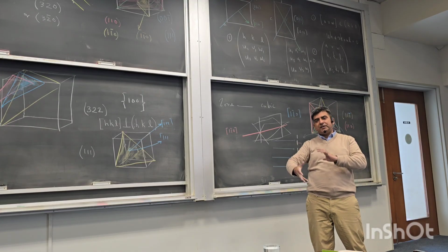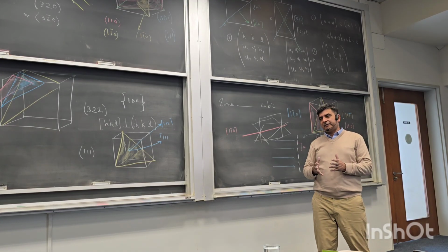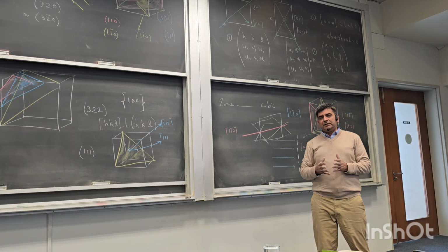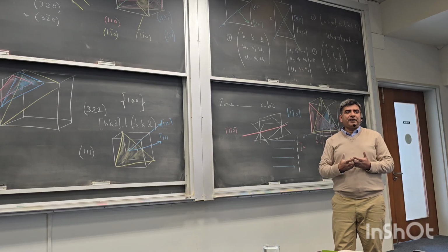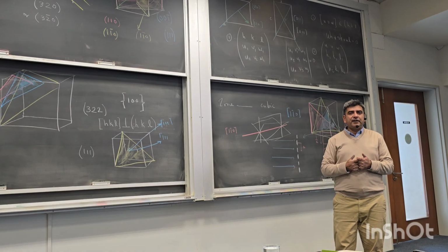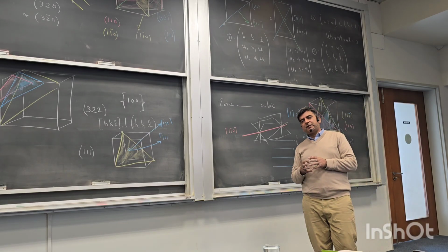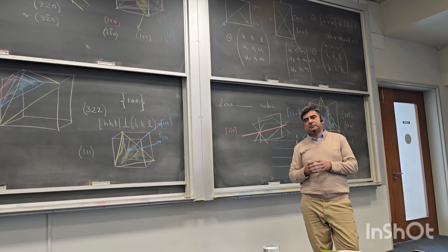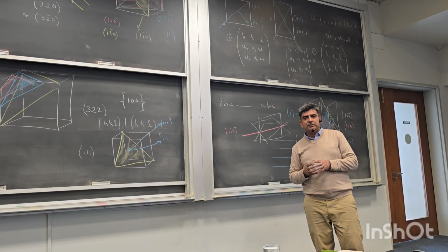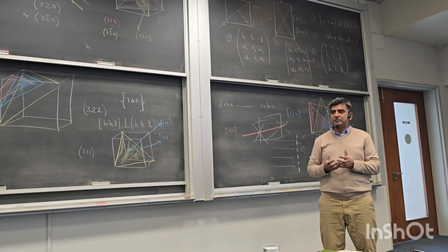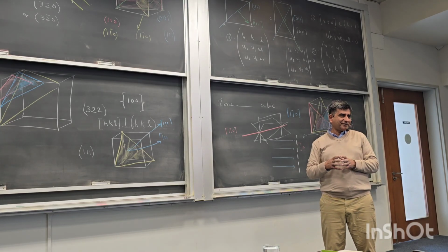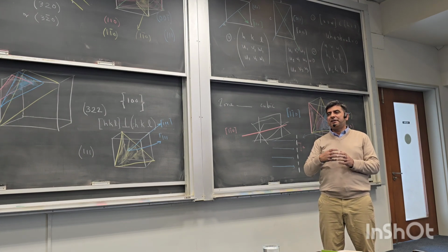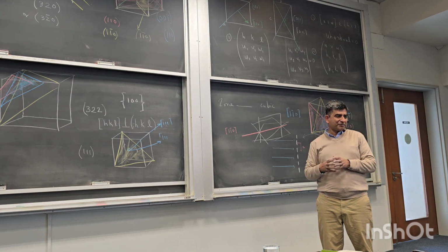Now crystals, of course, are the epitome of periodicity. Everything is arranged in a very nice symmetric fashion. So they act like gratings for radiation. If you shine X-rays, which are electromagnetic with short wavelength, they interact with the electron cloud. It is an electrostatic interaction, and iron, nickel, all of these elements have their own electronic structure. And they are arranged in a periodic fashion dictated by the space group to which that material belongs.